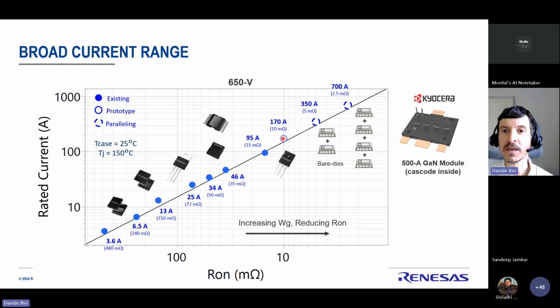And of course, if you need even more current, you can always parallel chips, and we have demonstrated, we're going to publish data on paralleling cascode chips to achieve 350 amps or 700 amps of current. You can see here a module integration by Kyocera. This is a 500 amp GaN module, and it's claimed to have cascode inside. And thanks to our sources, we think that there's Transphorm GaN in this package. So, a very elegant automotive package with GaN cascode in it.